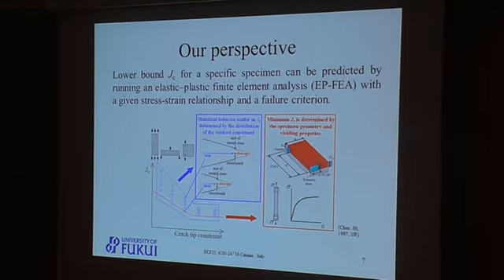We first sought to re-examine Chen et al.'s opinion that it is necessary to distinguish the minimum fracture toughness, or the lower boundary values of toughness, from the scatter band of toughness. The former is a definite parameter determined by the specimen geometry and tensile properties, and the latter is a statistical behavior determined by the distribution of the weakest constituent. We interpreted Chen et al.'s opinion as meaning that at least the lower bound JC might be predicted by running elastic plastic finite element analysis, EPFEA, with a given specimen geometry and a failure criterion.